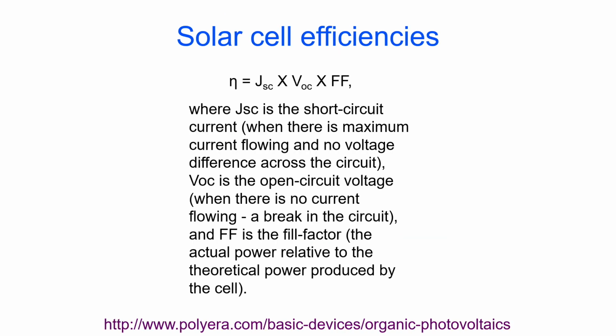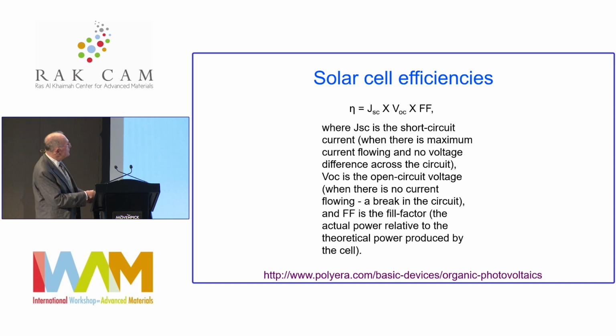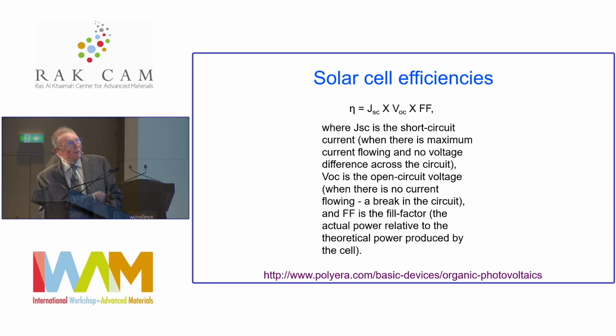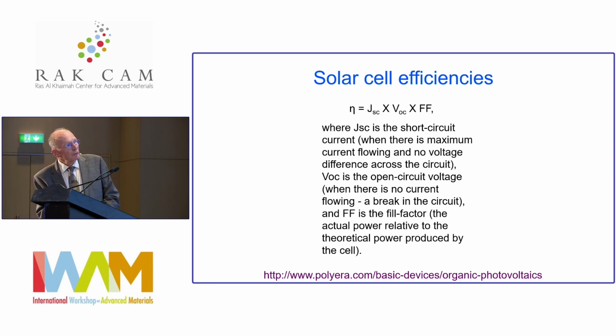Now, organic thin film solar cell efficiencies and solar cells in general are measured by their efficiencies, which are determined by the product of three components: the short circuit current, the open circuit voltage, and the fill factor, and these are described on this slide. And just to give you a ballpark figure, this can't be much greater than about 1 volt for organic materials, for reasons I'll show you in a minute. And this is for good devices in the ballpark of 15 to 25. 25 is about the best, it's coming up so far.